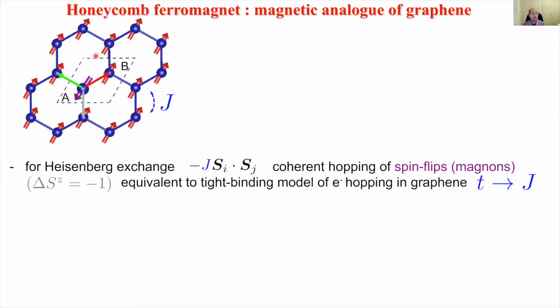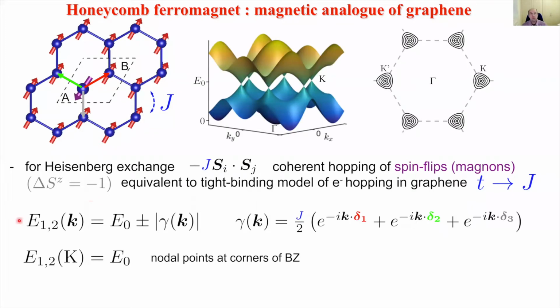Okay, so now consider that we flip a spin on one side, and through the exchange terms, then this spin flip can hop onto the neighboring sites, again on the same links as before, with the only difference now that the hopping T is replaced by the exchange interaction J, and now we have a boson, an excitation with delta SZ of -1 relative to the ground state, which hops. But formally, we obtain the same dispersion relation, only offset in energy.